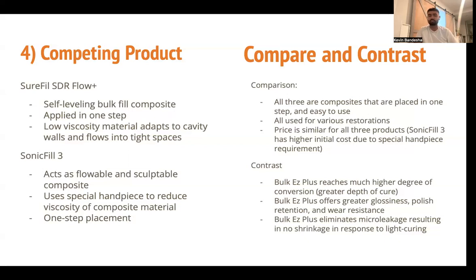Comparing these products, Bulk Ez Plus has a much higher degree of conversion, which leads to a greater depth of cure. Bulk Ez Plus also offers greater glossiness, polish retention, and wear resistance, and it eliminates micro leakage, which makes it so it doesn't shrink in response to light curing.